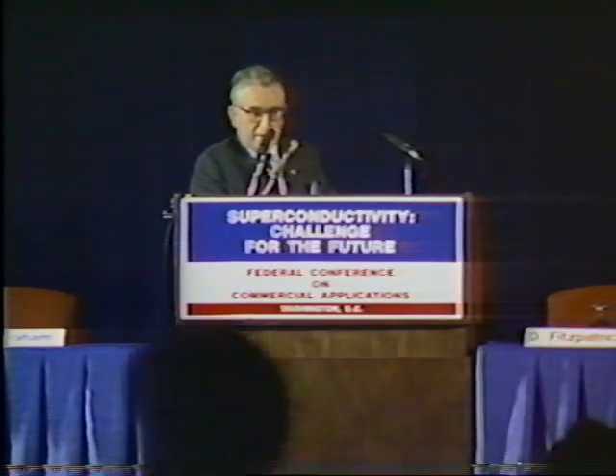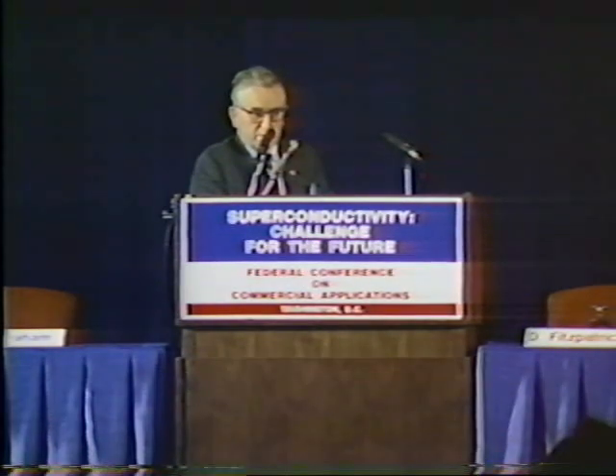I wanted to say a couple of other things that relate to non-magnetic applications. I'll just mention them in passing. If I could have the next slide, please. This was an indication of the filaments in the conventional conductors used today. The superconductors are broken up into many, many fine filaments. I don't think this will be as critical in the case of the high-temperature materials because of the greater stability to heat absorption at the higher temperatures. So it may be possible to work with much larger diameter filaments than in the case of the niobium titanium or niobium tin. Next slide, please.